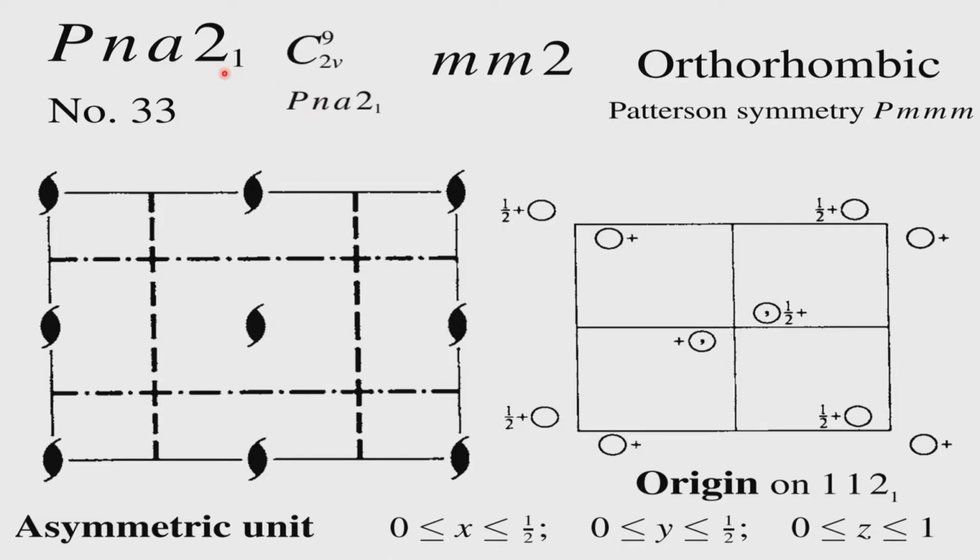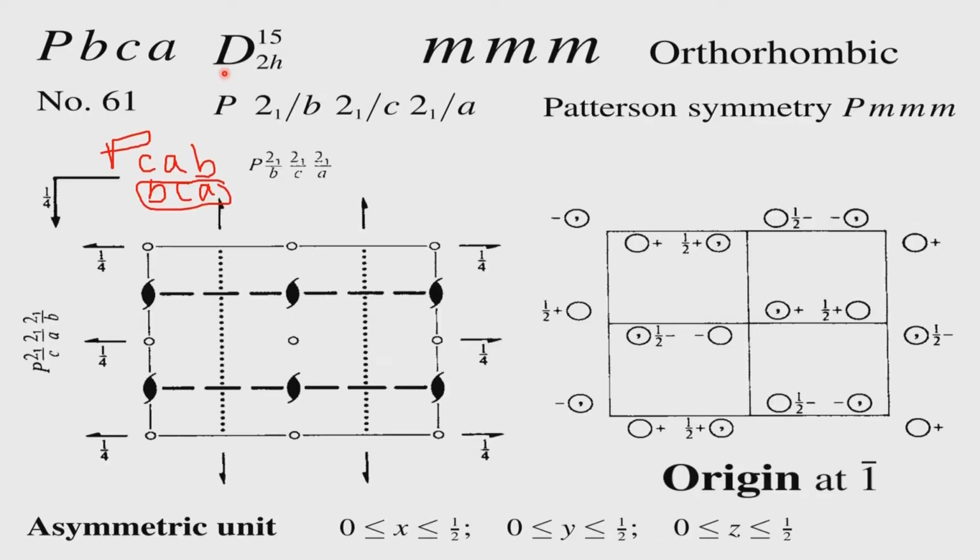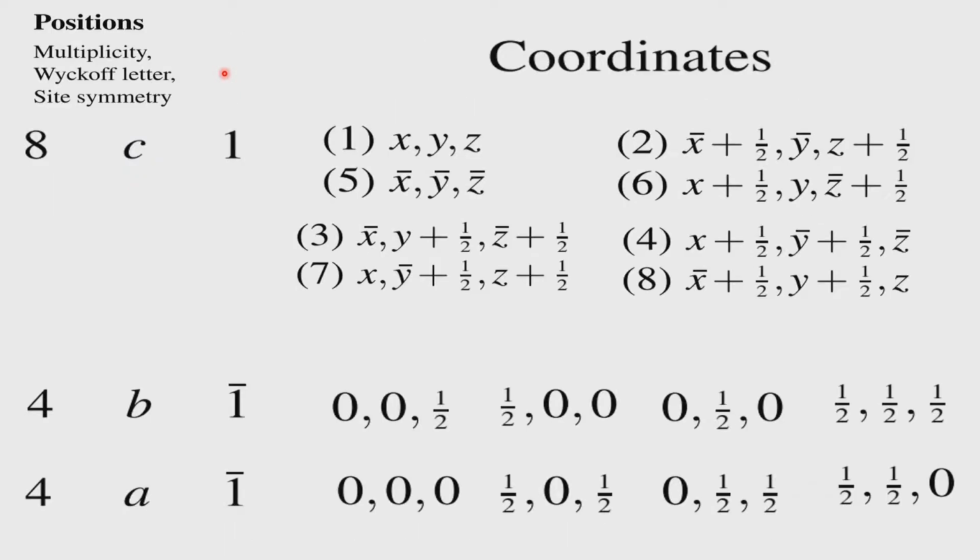like ferroelectricity or ferromagnetism shown in that particular direction, and you want that to be the z axis because your crystal is grown in that particular direction. It is very clearly seen in the morphology of the crystal. Then we would rather maintain that particular space group rather than report the standard space group. So this is something which you should bear in mind and never get into troubles when you discuss this.